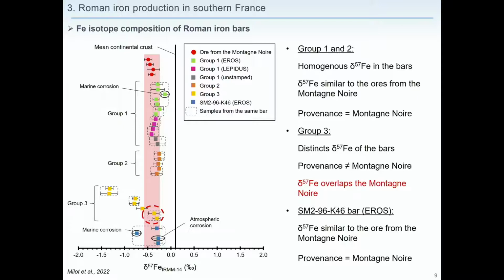And here we have two bars with composition similar to that of the Montagne Noire. So here we cannot exclude the major problem for every elemental and isotopic tracer: we can have overlapping composition between distinct sources. And then we also analyzed a last bar here, which didn't contain enough slag inclusions to make a trace element analysis. And except for the corroded sample, this bar has composition similar to that of the Montagne Noire. So we suggest a provenance from the Montagne Noire, which is in accordance with the Eros stamp of this bar, like for the green bars here.